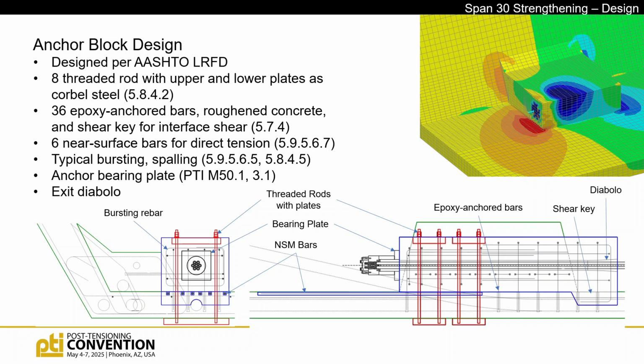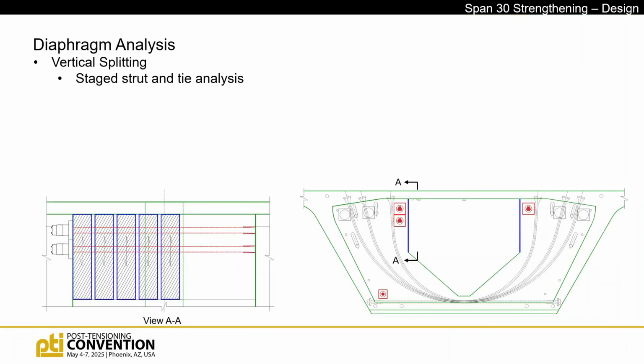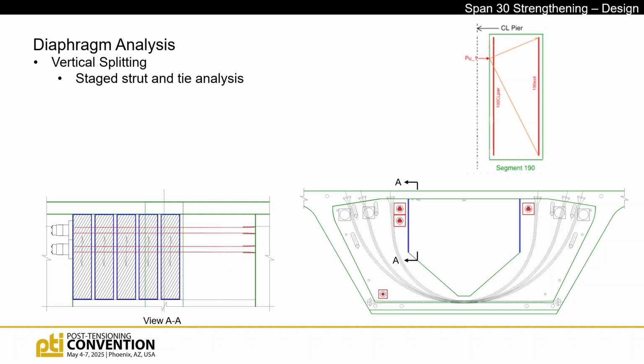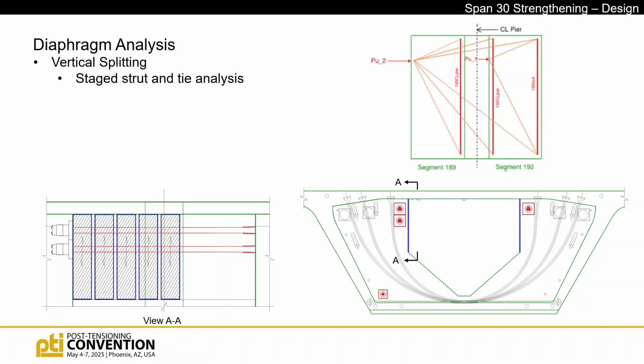And then we had an exit Diablo on the end to give Jason and his team a little bit of flexibility with the geometry. Now with the diaphragms, for its design, we had to do a staged strut and tie analysis to look at the vertical splitting that took into account the way it was originally constructed. So inside a closure pour, before there was a closure pour, you have the original tendons, and they impart some stress on those rebars on the exit face. And then you have additional stress that comes in with the later tendons that were stressed, and then, of course, the tendons that we're adding in.